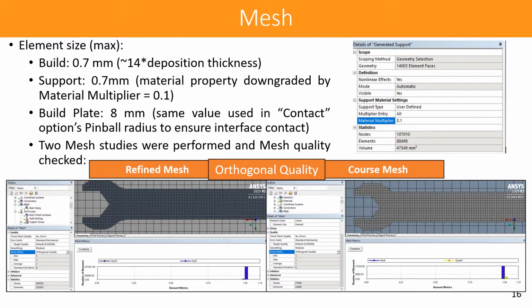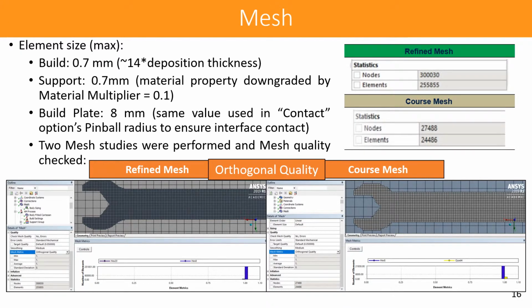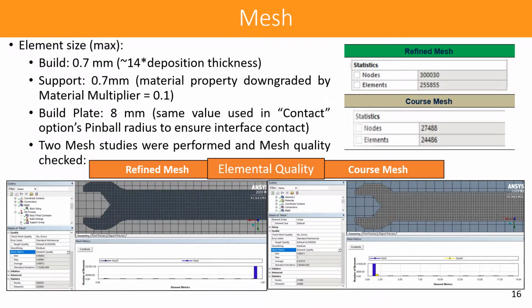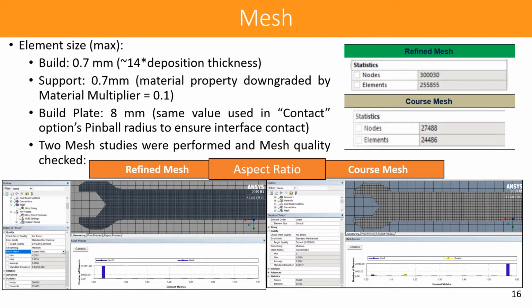Individual part maximum element sizes are set after a coarse mesh study, with the smallest size allocated to the build part. Normally, the mesh size should be 5 to 15 times the deposit thickness. In this case, the deposit thickness is chosen as 50 micrometers, so the selected mesh size is 0.7 millimeter, and for the base body, the mesh size is 8 millimeters. The refinement significantly increases the elements and nodes. After careful study of the mesh qualities by checking the orthogonal quality, mesh elemental quality, skewness, and aspect ratio for hexahedral elements, the refined mesh is chosen as the final mesh for analysis, although it significantly increases the number of nodes and elements.